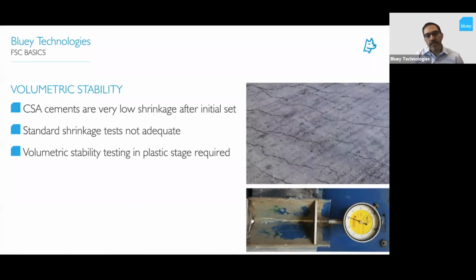But what's happening in the first 7 days, and particularly with something that's curing so rapidly, you really need to know what's happening. So we do a volumetric stability test during the plastic stage, and we're actually monitoring the volume movement and change during those early stages, because we know that that's a high risk with calcium sulfoaluminate cement systems, is that you can get plastic cracking in those early stages. Some of you may have had experience in seeing that out on sites. If the product is developed well, you won't see that plastic shrinkage cracking.